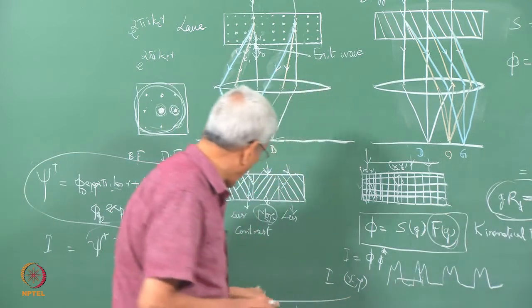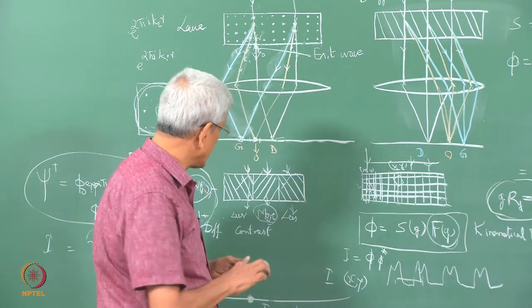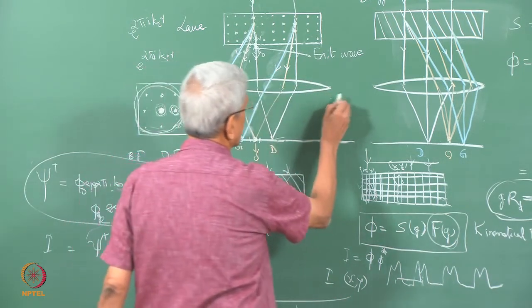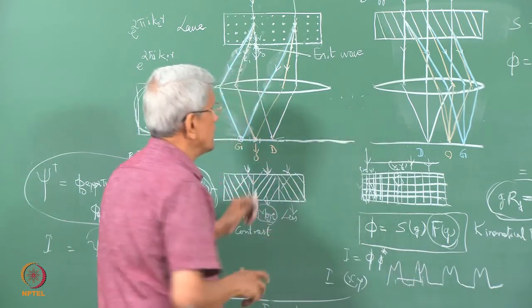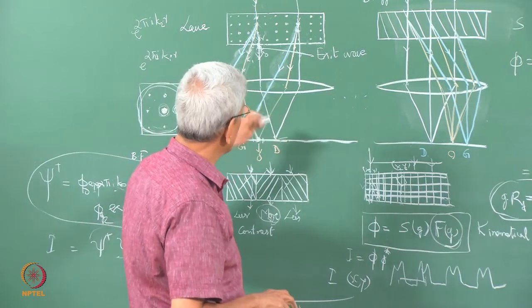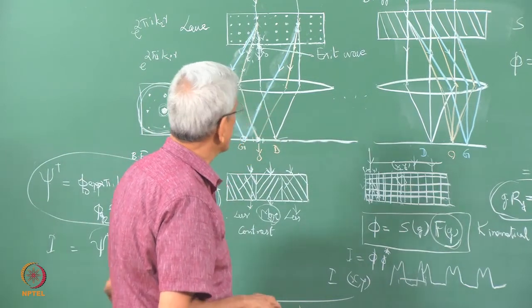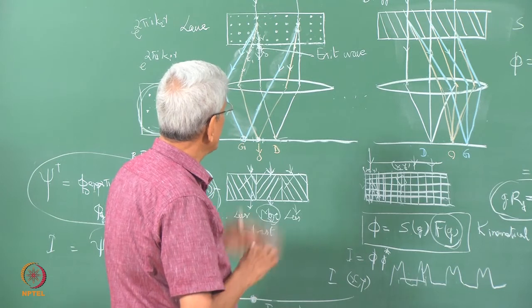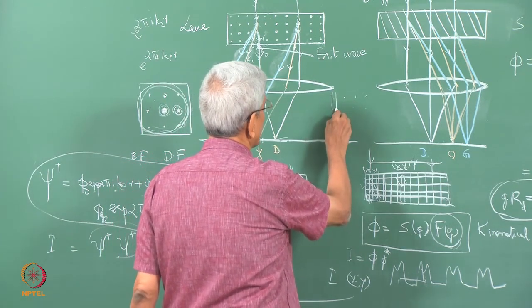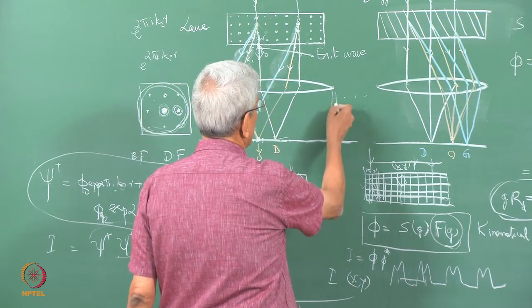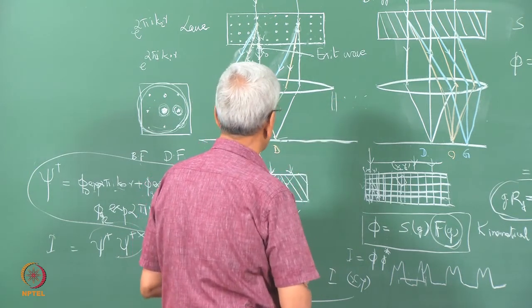Then what we are essentially getting on that image is nothing but a dotty contrast. This dotty contrast has some relationship to the distribution of atoms along the columns. Not the distribution of atoms; it has something to do with the columns in which the atoms are present in the sample.